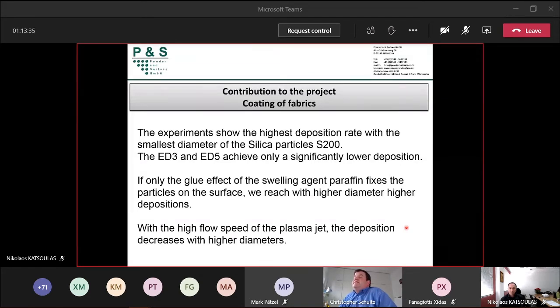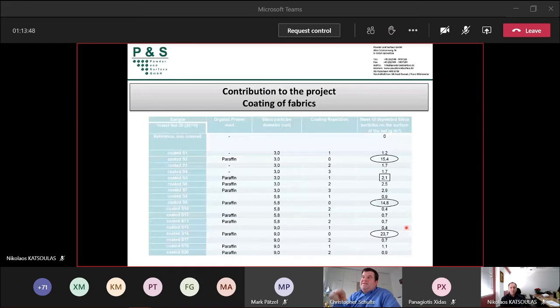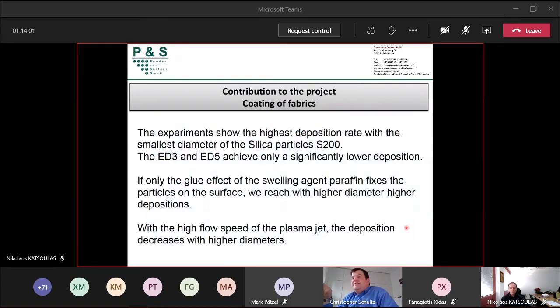Okay, but with this test on the side, there was a very interesting idea. If only the glue effect of the swelling agent paraffin fixes the particles on the surface, if you go one page back, you can see the roundabouts about these points. There's a deposition without plasma jet, only with a swelling agent itself. Okay, go back, please. And then you can see we reach higher depositions with higher diameter. And this glue effect is a strong effect. So it brought up the idea to use an adhesive. I will show this later in the presentation.